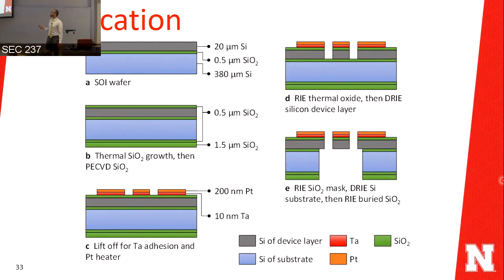The next step is to do front side etching, which will give you the actual shape of the device. And this was by reactive ion etching for the front silicon dioxide, and then deep reactive ion etching for the silicon device layer. The last step is to release the device to make it completely hanging in vacuum by etching the backside by reactive ion etching and deep reactive ion etching.